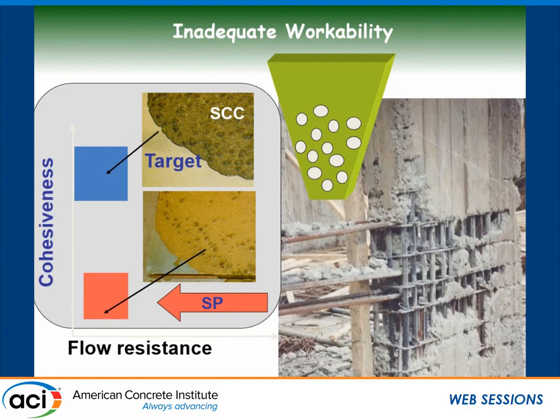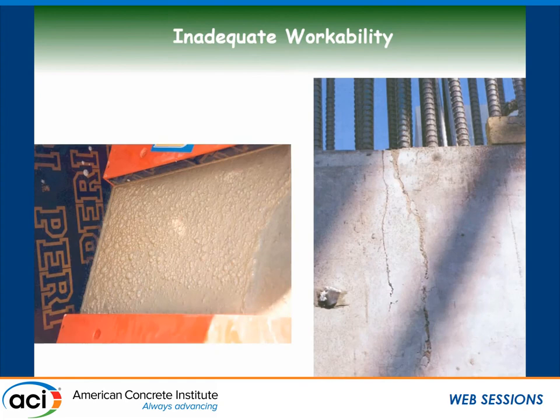Now, if you don't know what you're doing, this is what you get. And this is an actual job site from an SCC project where it was decided by someone that instead of putting superplasticizer and reducing the flow resistance, they just added water to make the concrete more flowable. But when you add water, you are also reducing viscosity. So the concrete has low resistance to flow, but also very low cohesiveness. And you get issues with blockage and lack of filling ability and passing ability.